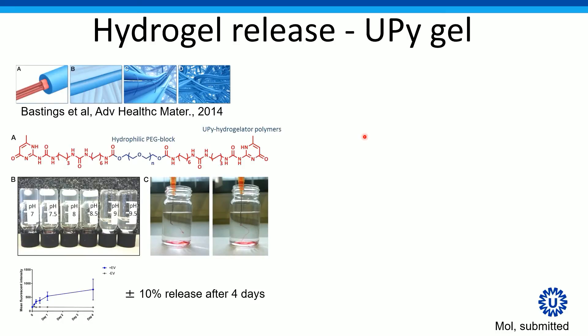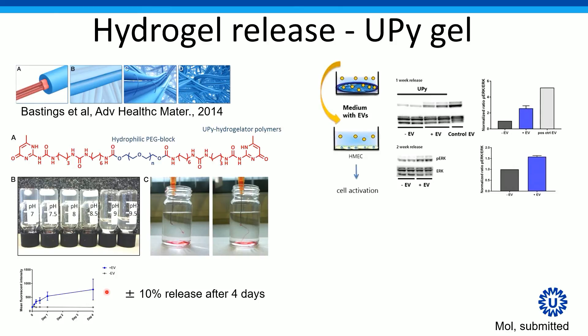For those reasons, we are also developing different hydrogels. This is a hydrogel published a few years back from the Eindhoven University of Technology — basically a gel with block polymers and different side chains that allows it to be a pH-switchable gel. At neutral pH it's a hydrogel; at high pH it's liquid. That allows us to inject it via a catheter into the myocardial environment, where at pH 7 it becomes a gel. What we did is mix in our vesicles and we could show that these vesicles are slowly released from these particles. Of course this is just one of many hydrogels you can use. Within one to two weeks after release, these vesicles are stable in a regular culture dish and can still activate as I showed you before. So these are relatively stable in a gel and can release their therapeutic benefits.